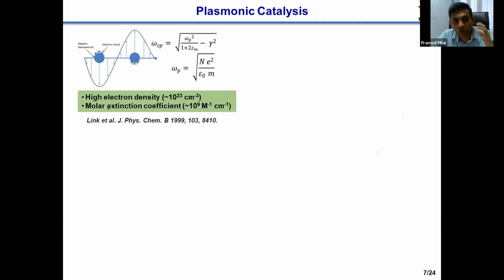Because of this, the molar extinction coefficient of plasmonic nanoparticles is very high compared to a normal organic or inorganic chromophore. For example, the best of the best dyes that you know have a molar extinction coefficient in the range of 10^4 to 10^5 per molar per centimeter. Whereas plasmonic nanoparticles exhibit the highest molar extinction coefficients of any material prepared by mankind. So this is the impact of surface plasmon resonance. It essentially means that all the electrons present in the plasmonic nanoparticle can be used to carry out chemical transformation. This is the main point here. A plasmonic nanoparticle is a storage of a huge number of electrons which can be excited with appropriate light, and if you can do a proper reaction, you can use all these electrons to carry forward chemical transformation. This is one advantage of working with plasmonic nanoparticles that you don't see with non-plasmonic materials.